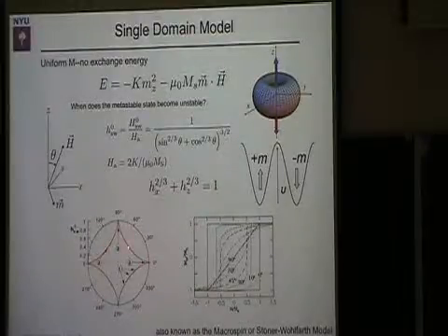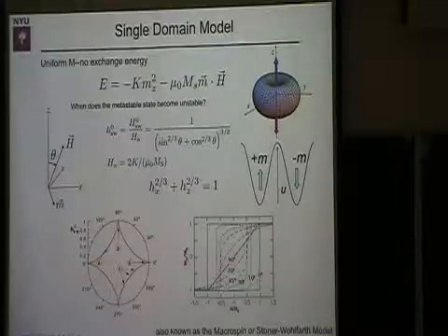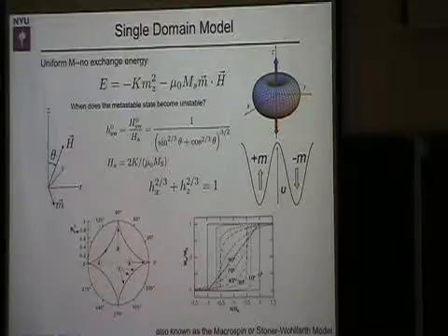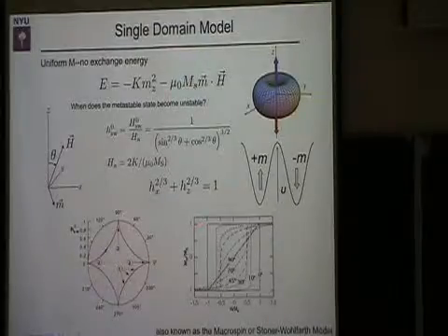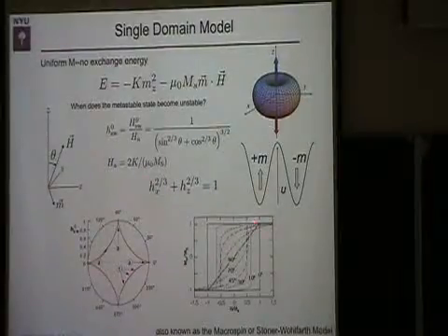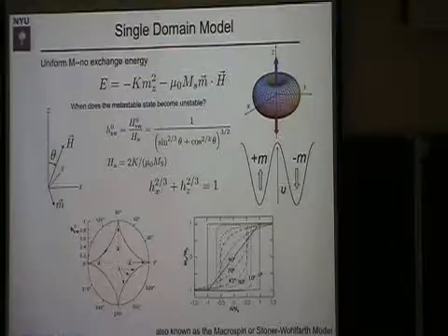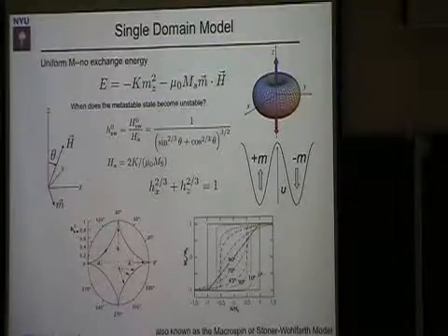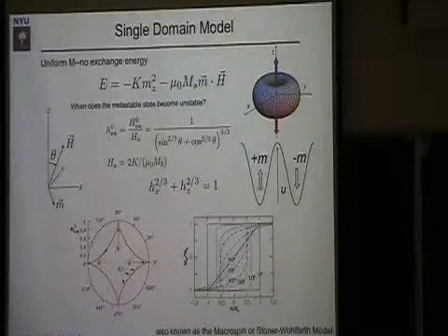Actually, in magnetism, there was something known as Brown's paradox. The fact is, whenever you measured small particles, you could measure the anisotropy by saturating the sample along the hard direction. And when you looked at switching, you always found the magnetization switches at much, much lower fields than predicted by this model, which indicates this model is not really describing the physics.